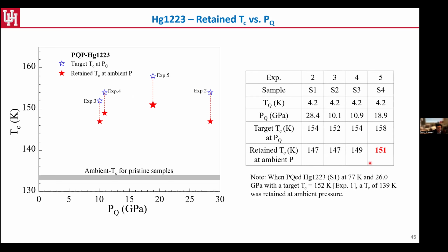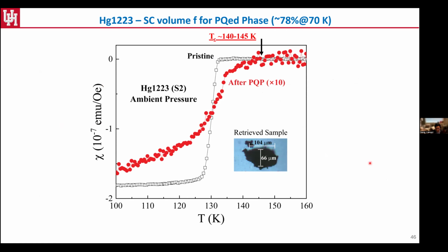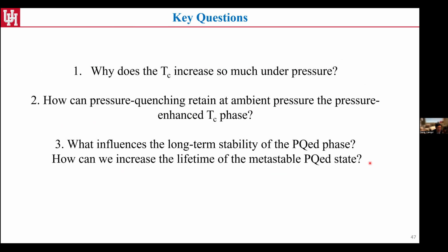So from the TC point of view, that's really very exciting. But of course, we were able to recover the sample and also do magnetization measurements, and prove this effect is also bulk in nature. So after that, at least for us, we're pretty convinced that this technique works for retaining the high-pressure enhanced TC back to ambient.